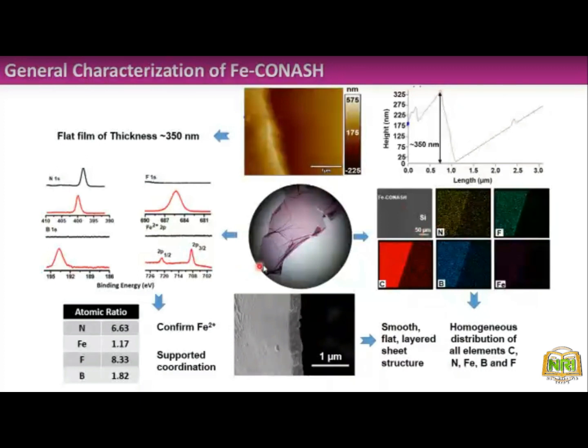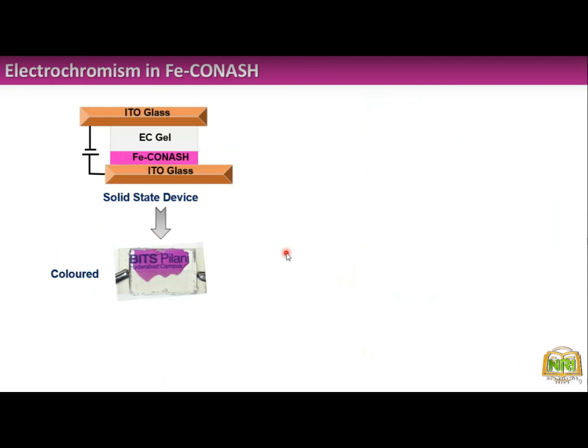So the coordination nanosheet is already formed, and we have seen that the thickness we got after keeping it for 2 days is 350 nanometers. Okay, and from XPS we have calculated that the iron 2 plus structure is present here. Now, coming to the electrochromism part.